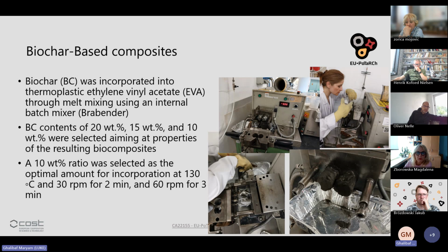The work was the optimization of the ratio of the biochar, and we selected from 10% to 20%, but then we found out that the 10% ratio was the optimal amount for this incorporation. Below the picture you can see that if we added more biochar, it could not be incorporated. That's why we understood that we have to change the amount of the biochar.